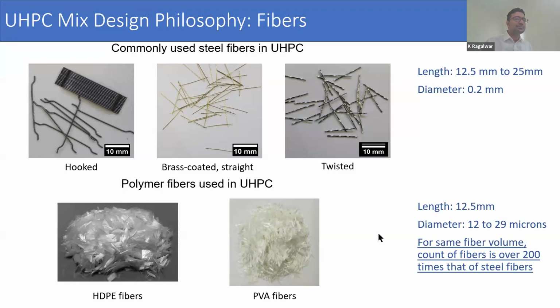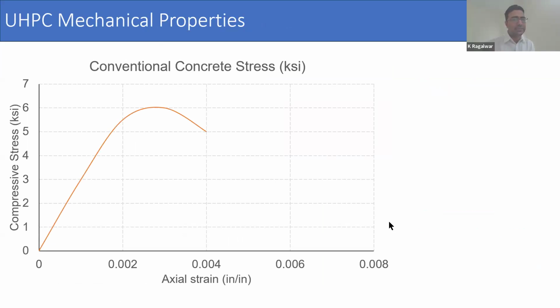So what that does is, for the same fiber volume, the count of fibers is over 200 times that of steel fibers, and that gives you more bridging when the concrete cracks. However, the downside is that these are difficult to mix, and you need specific viscosity. You need to control the viscosity of the paste so that any polymer fibers are uniformly dispersed in the concrete, because as per definition, as you remember, UHPC contains discontinuous fiber reinforcement, and it should be randomly dispersed. So now we look at the UHPC mechanical properties.